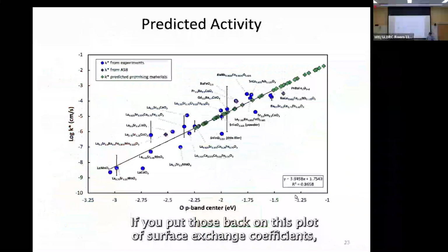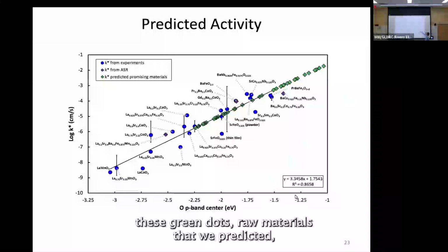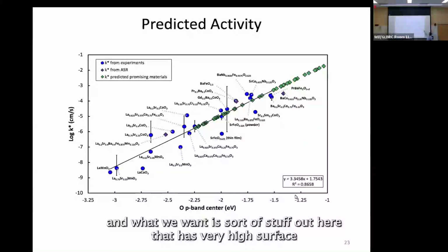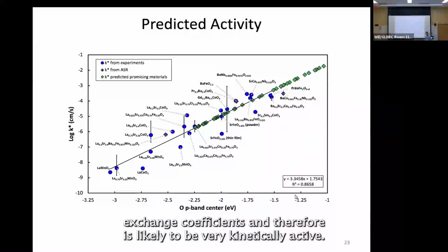If you put those back on this plot of surface exchange coefficients, these green dots were all materials that we predicted. And what we want is sort of stuff out here that has very high surface exchange coefficients and therefore is likely to be very kinetically active.